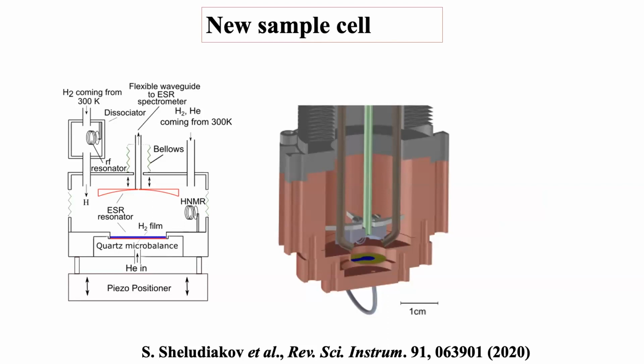After many tries, we couldn't create a big, thick sample and stay within the bandwidth of our spectrometer. When we failed at this, we realized we hadn't found a way to use this scheme of experiment. But we found that if we make a thin film, we can follow the propagation of the hydrogen atom in H2.